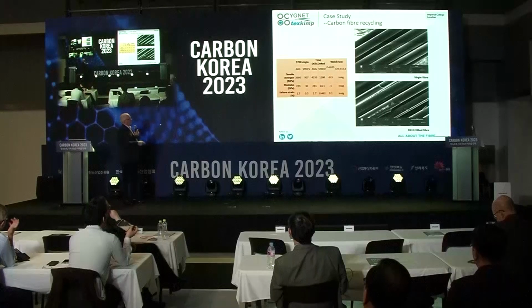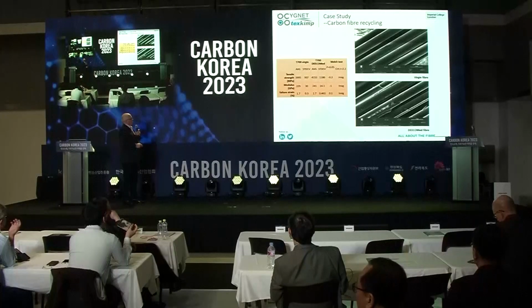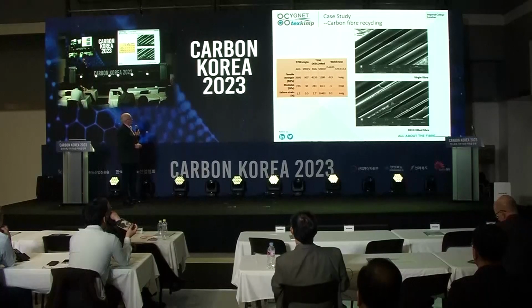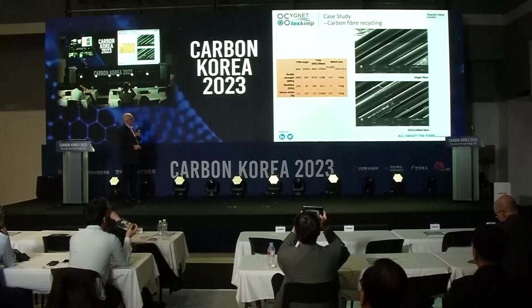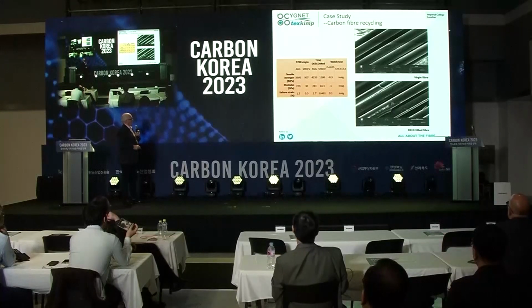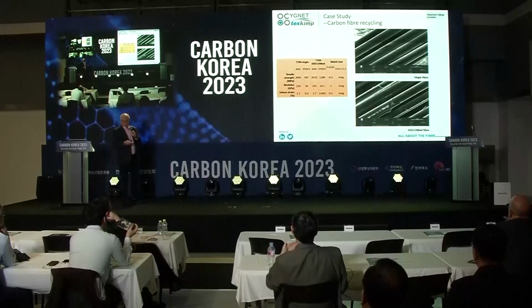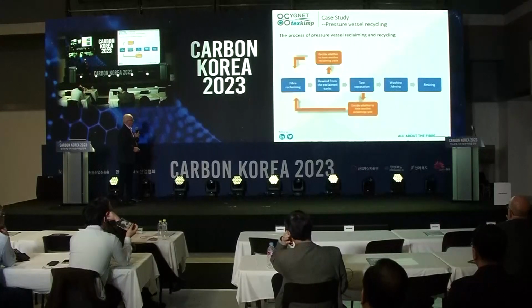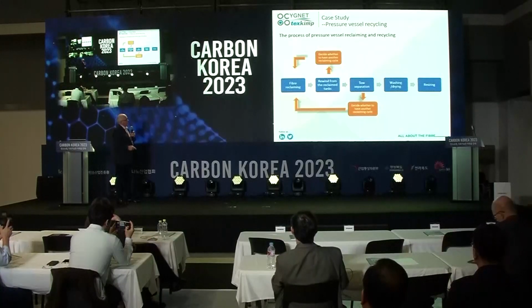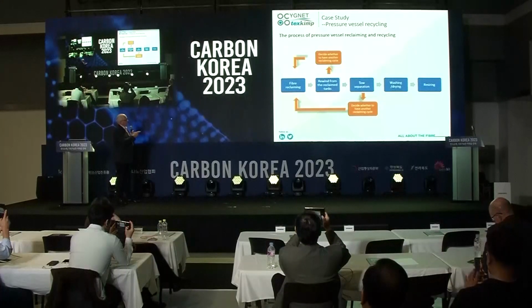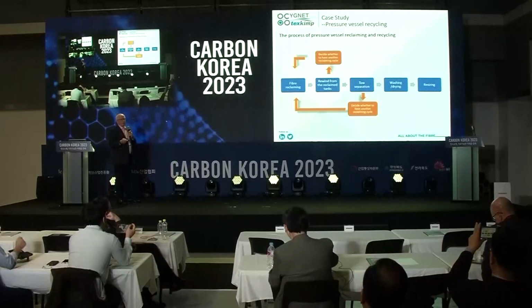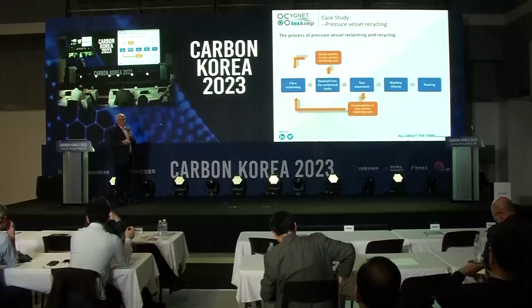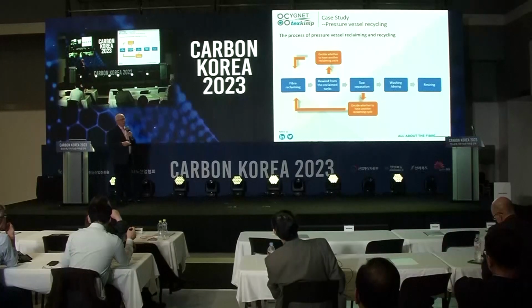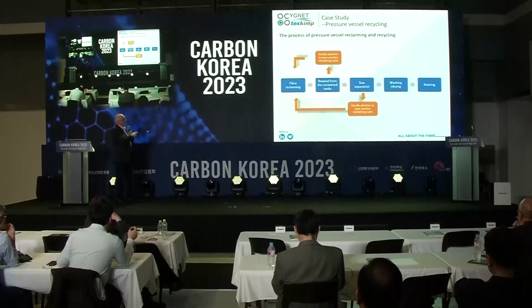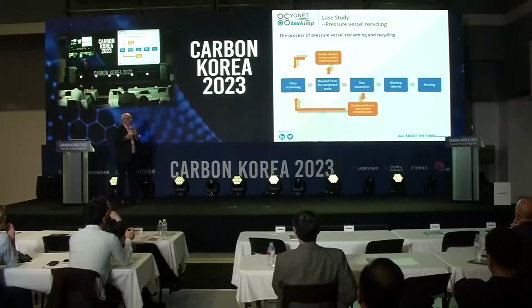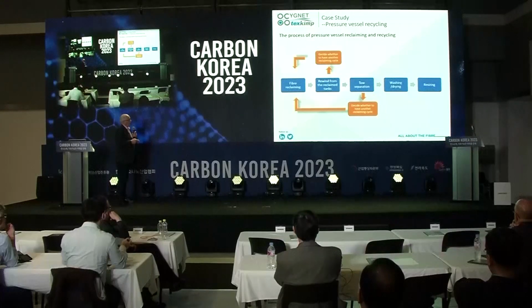You'll see here on the side some results which quite frankly flabbergasted me, but these are from Imperial College in London. They did testing for us, and we're basically finding no mechanical degradation at all. So the process that we're going to go through with this is taking it in several steps to see how things work. We've got to work out the length of time and the processing conditions for each type of material that we're going to use. And so it's an iterative process to get down to this final recipe of conditions that we're looking for.